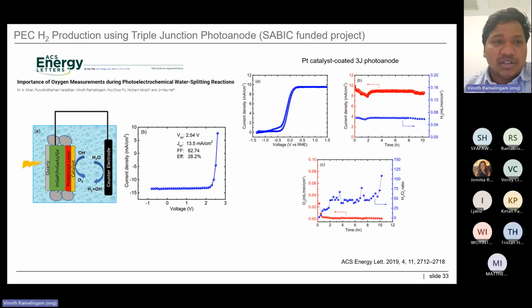This is one of our works that we did at KAUST. This is a SABIC funded project where I was also involved as a part of this project. The ultimate aim of this project was to use a triple junction, which is indium gallium phosphide, indium gallium arsenide, germanium photoanode for water splitting reaction. But during this project, we found something interesting. What happened when we coated Pt, without any protection layer, on the rear side, and used this as a photoanode for water splitting reactions? You see here, during the water splitting reaction, we can see stable hydrogen production as well as stable current density. But when we were measuring oxygen, there is no oxygen production at all, and it's also not maintaining the H2 to O2 stoichiometry ratio.